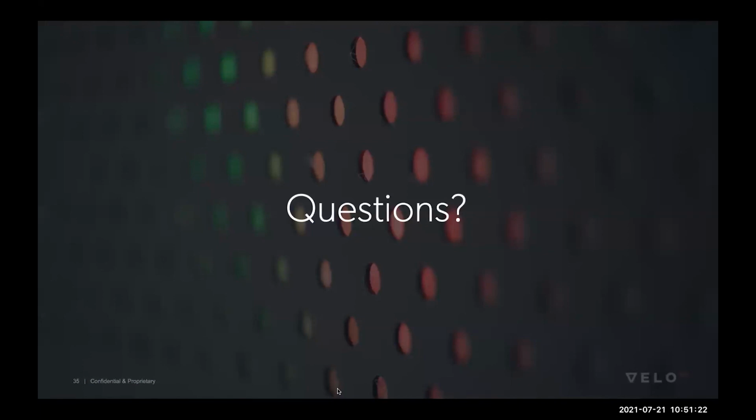And I might just elaborate on that, one thing that Will mentioned earlier. There are good candidates for free floating, and then there are candidates that just don't make sense. For large, massive parts where we're going to be putting a lot of high energy in, they don't tend to dissipate the heat as well. So we would probably opt for direct contact to the build plate on a large part that's going to generate a lot of heat. Yes, that's a great point, Gene. That goes as well when you start to get into very sophisticated parts: you want to make sure you're not thermally choking the part by having a ton of mass up top and not much of a conductive path to the build plate. Good point.